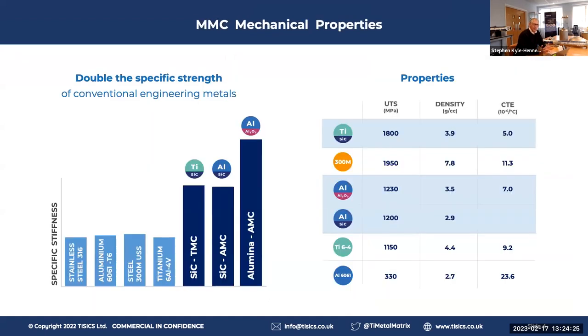So we've got some really, really clever materials within TISICS. They're about twice the specific stiffness and strength of conventional metals through our reinforcement. That's where we combine a ceramic fiber, silicon carbide or alumina, into aluminium or titanium alloys to give very, very high strength and stiffness. The material properties on the right show that for aluminium, we're about 4 times the strength of a really good aluminium, with similar density, a little bit higher than that. And we can significantly reduce the thermal expansion below that of aluminium.